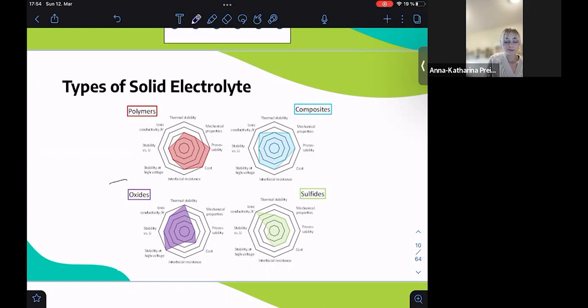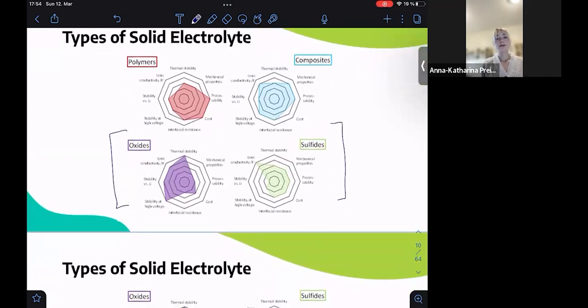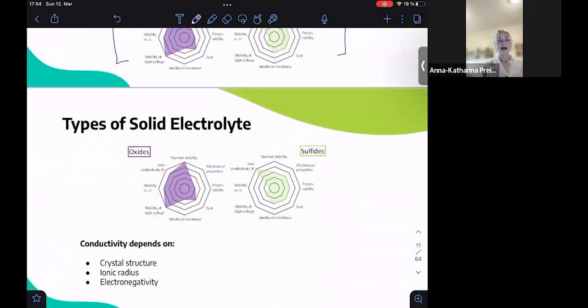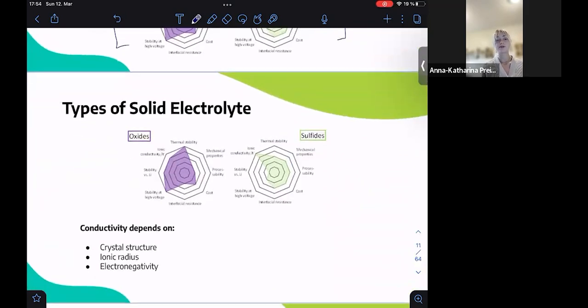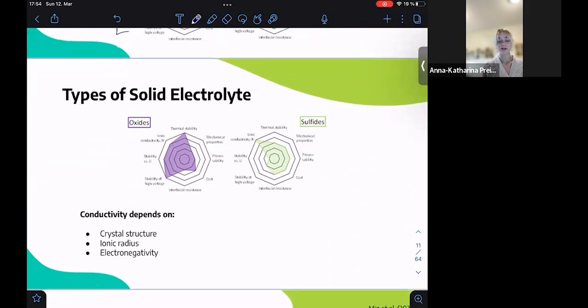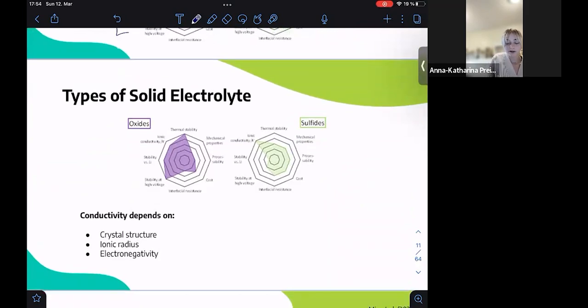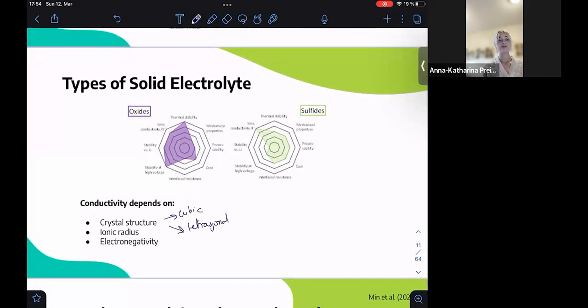used. In most research, we have ceramics, which include oxides and sulfides. And these are really great because they have high ionic conductivity and they're very stable over a wide range of temperatures, but they're also brittle and difficult to manufacture in large quantities. For ceramics, we can refer to the crystal structure to tell us how conductive that material might be to ions. And we often see that tetragonal or cubic structures have high ionic conductivity due to the presence of interstitial sites or vacancies that can facilitate the movement of ions through the material.